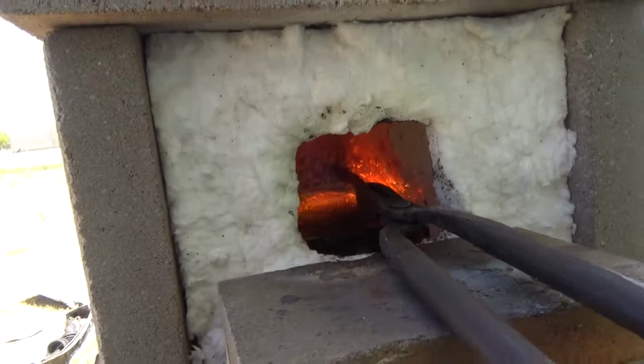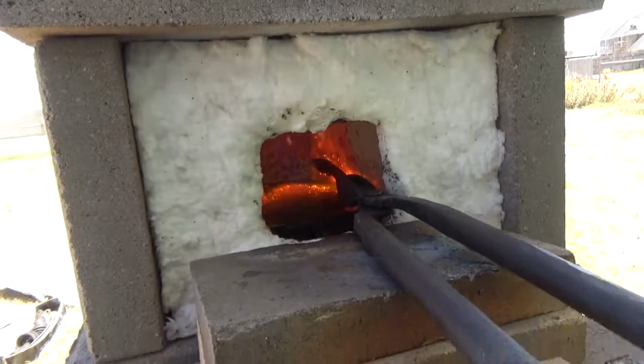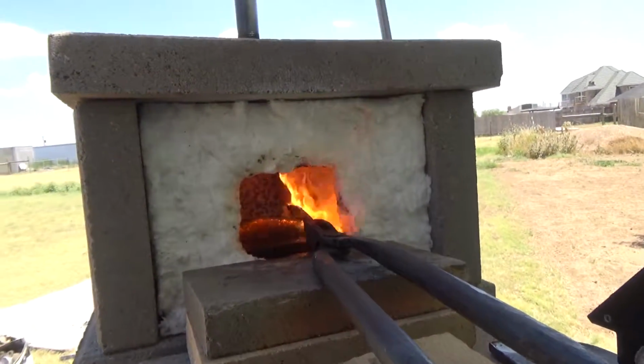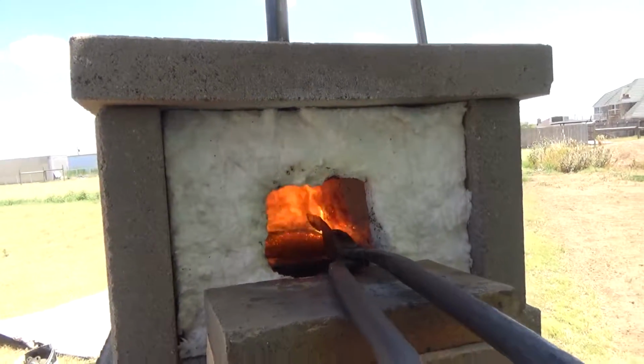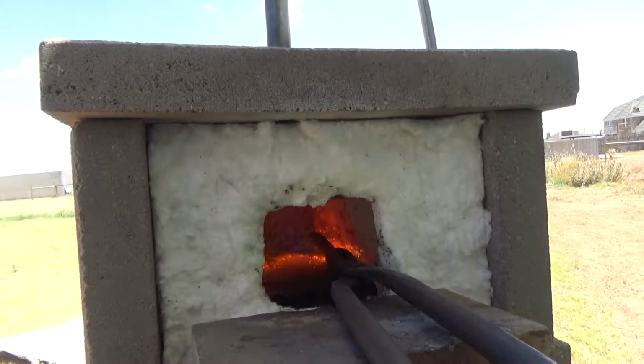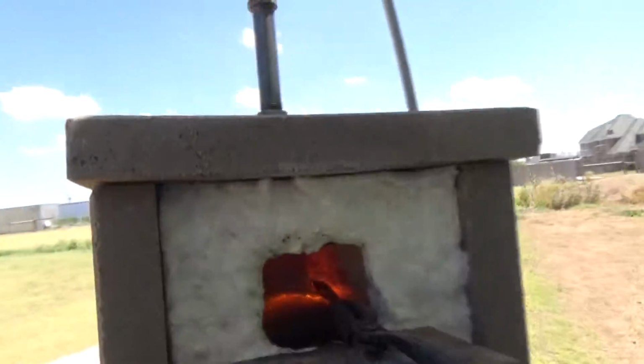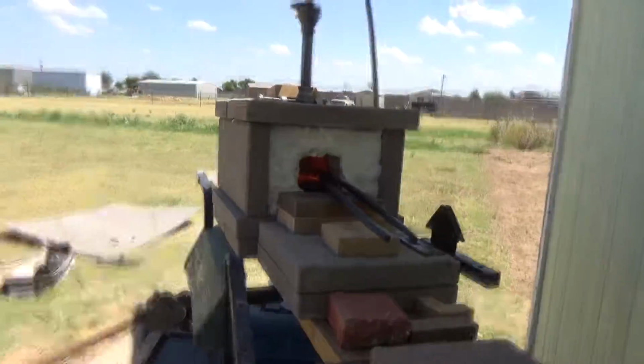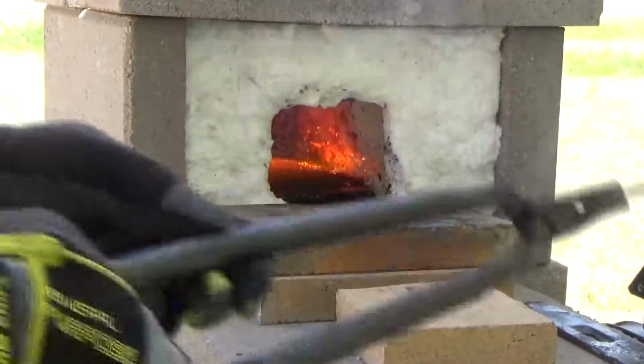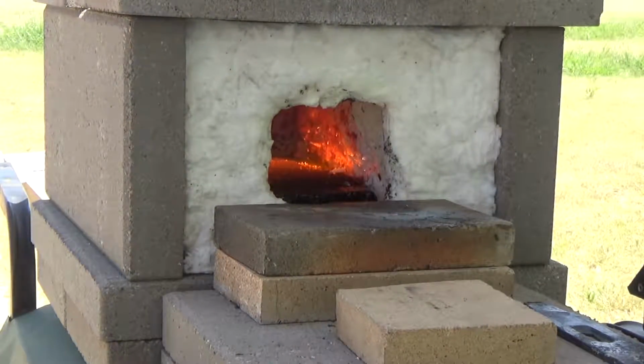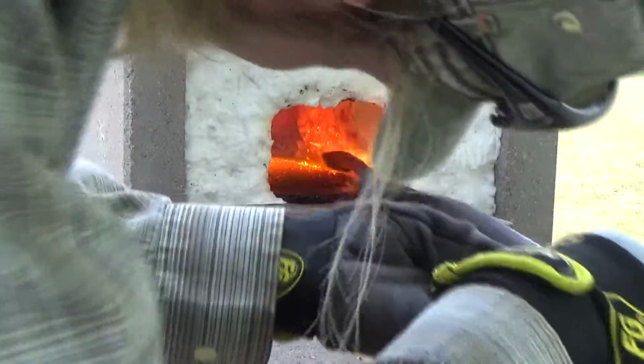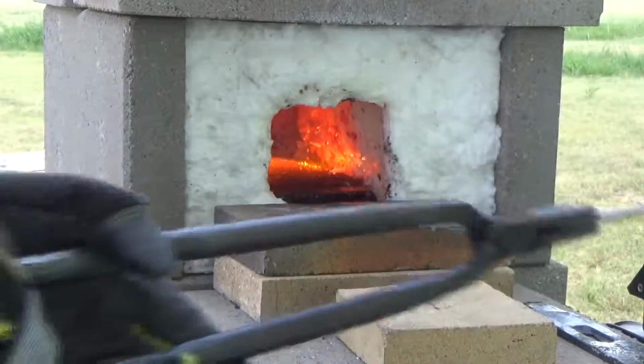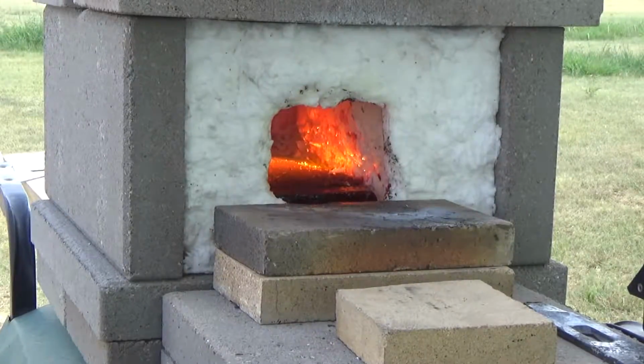You'll notice that now that it has been quenched, it is magnetic again. Though it is not austenite, it is still martensite. It's magnetic. So then I put it back in the forge for a final heat. And for the final heat, I go a little bit past what I have been, because 1425 is generally not quite hot enough. So I'm going to go a little bit past that to closer to an orange heat, medium to bright cherry, and then I'll quench the blade.